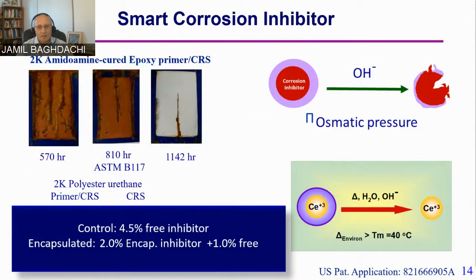Similar to something smart, for example, here. Folks, we put, or they put, not we, I don't do that myself. So we put corrosion inhibitor into coatings, like cerium, usually for aluminum. But by the time we end up with corrosion, the cerium is already gone. It leaches out. What if we put that inside a capsule, which we have done a long time ago? The military uses it right now, and then it only responds when there's corrosion.